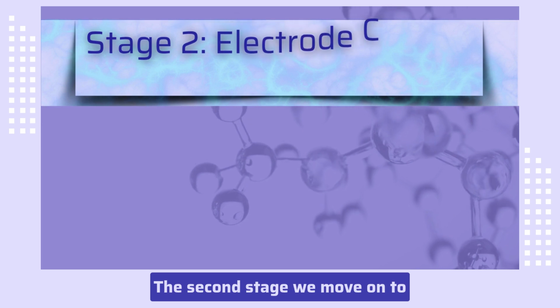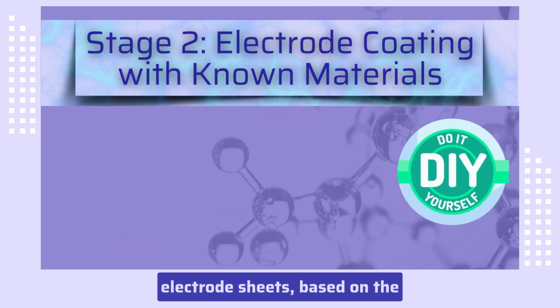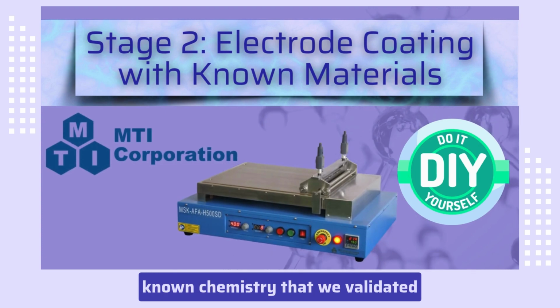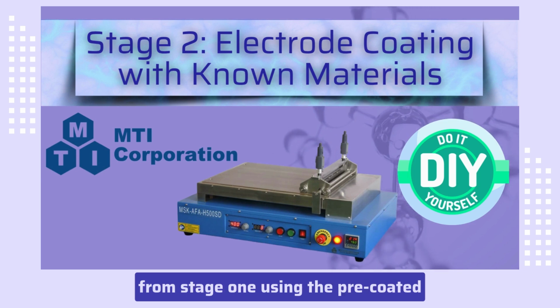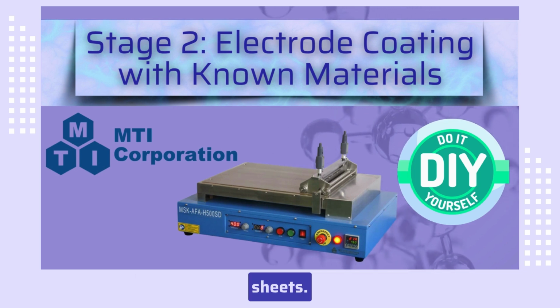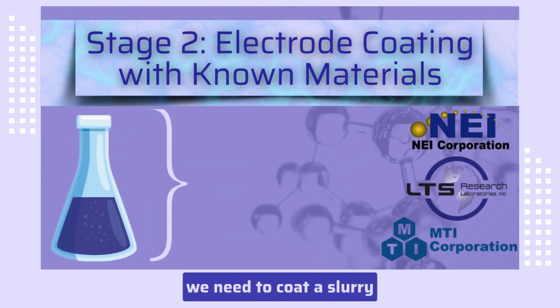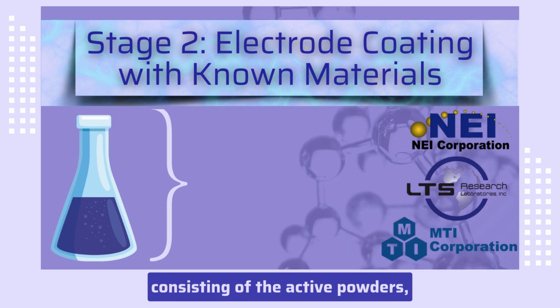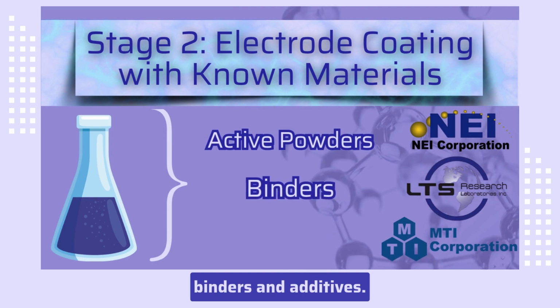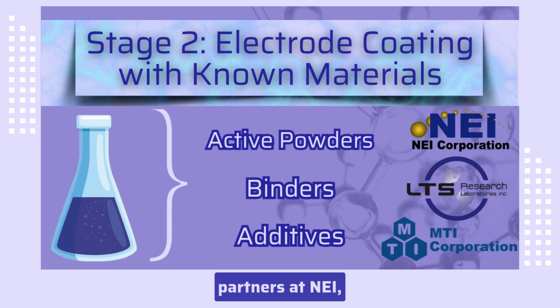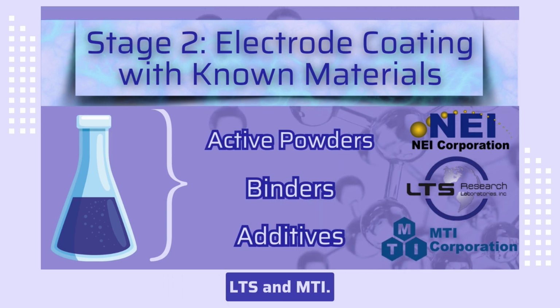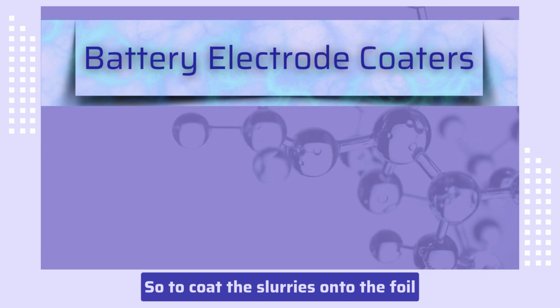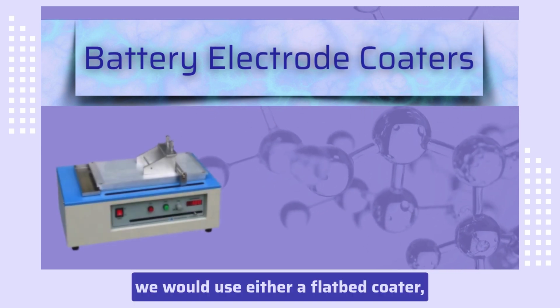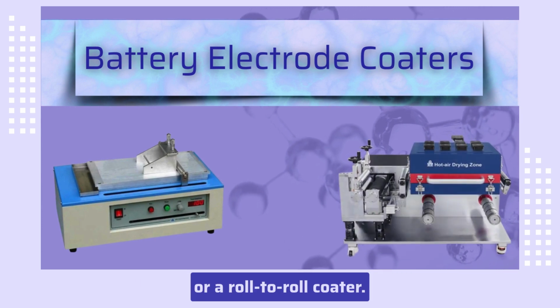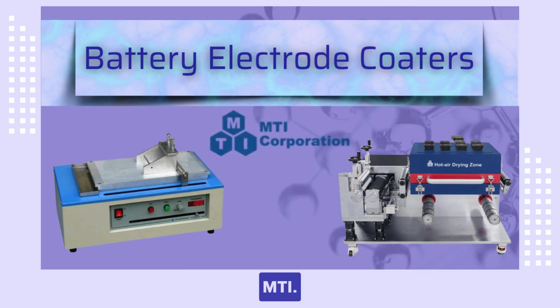The second stage we move on to is to then produce your own electrode sheets based on the known chemistry that we've validated from stage 1 using the pre-coated sheets. In order to do this, we need to coat a slurry consisting of the active powders, binders and additives, which are available from our partners at NEI, LTS and MTI. So to coat the slurries onto the foils, we would use either a flatbed coater or a roll-to-roll coater. Both of these are available from MTI.